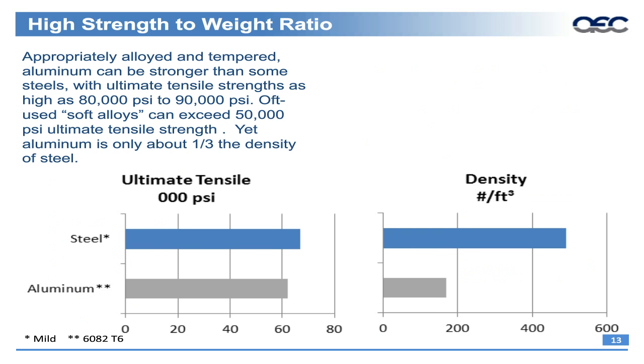With the high strength to weight ratio being a key attribute to aluminum, we can see here that in some alloys of aluminum, this one in particular is 6082 alloy, which is a structural alloy in comparison with mild steel. You can see that the ultimate tensile strength is much the same. However, the density of steel is much greater than aluminum. So when you look at it on a strength to weight ratio, you can sometimes yield a part that is almost nearly as strong as a comparable steel part, yet is a third as dense as steel, and therefore will typically weigh sometimes as much as half as the weight of the steel part.